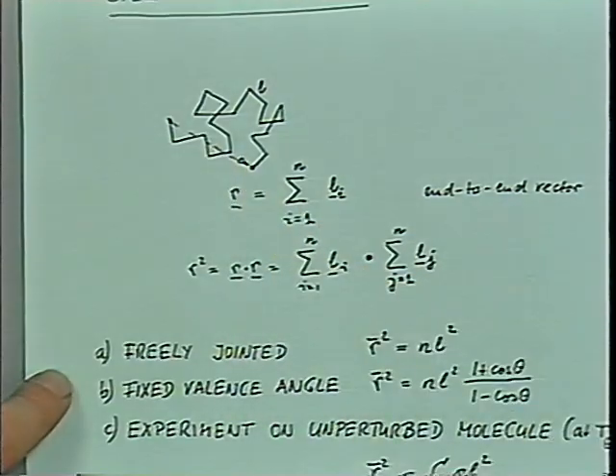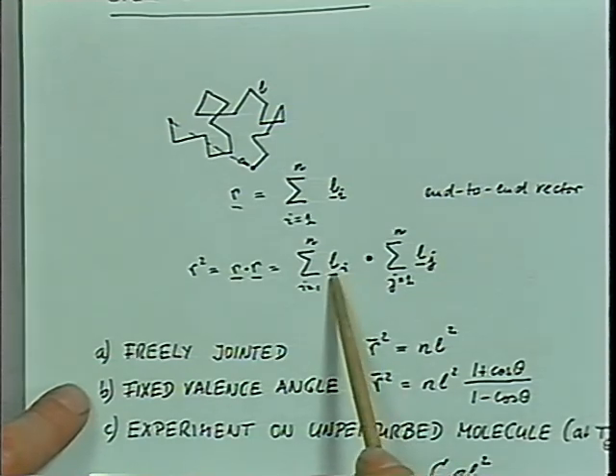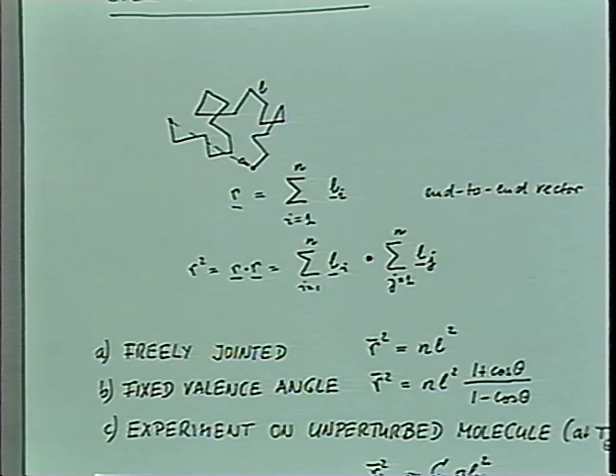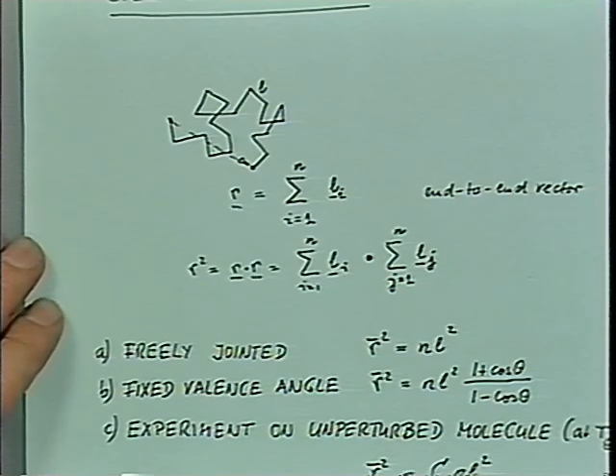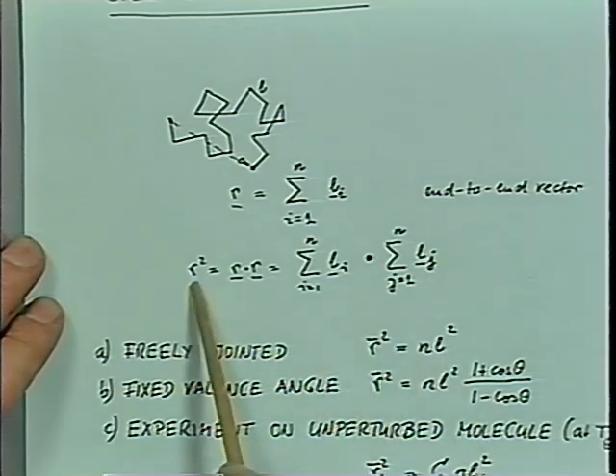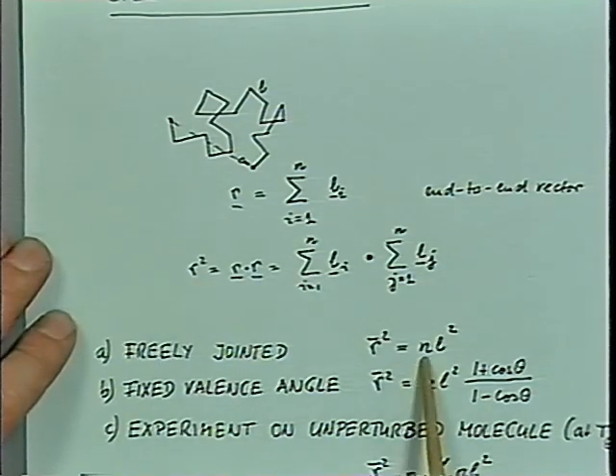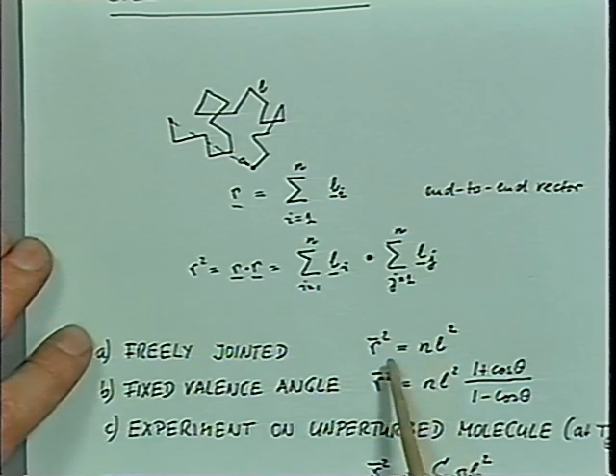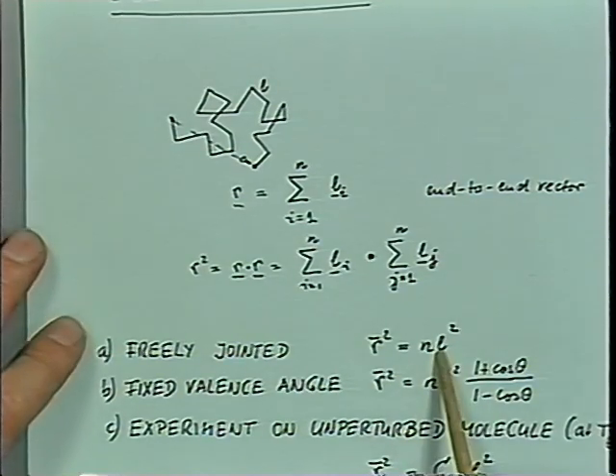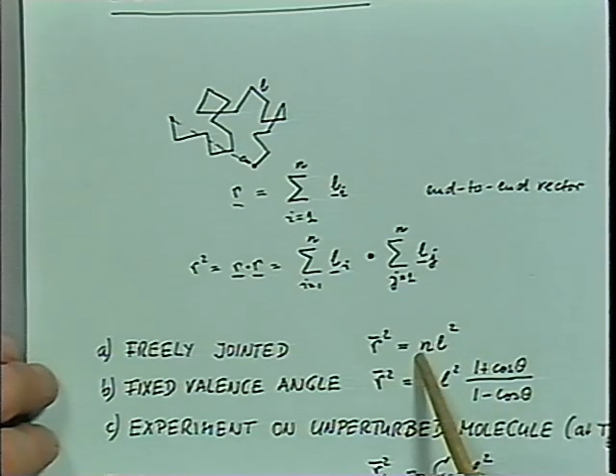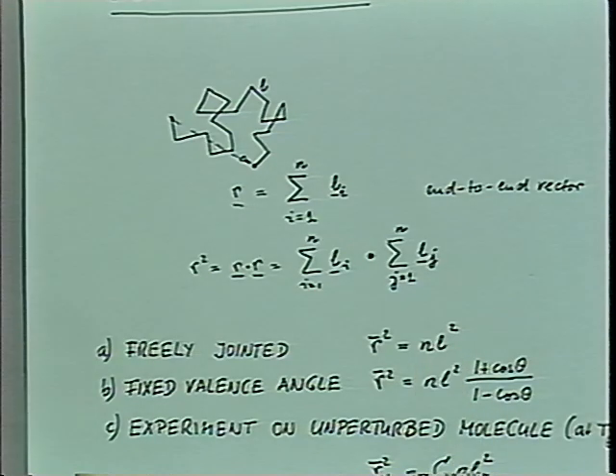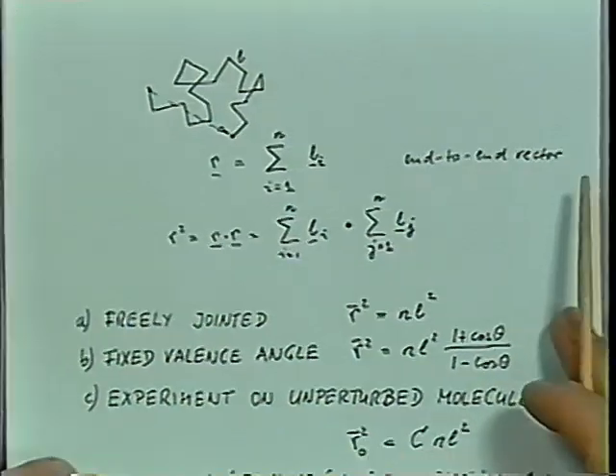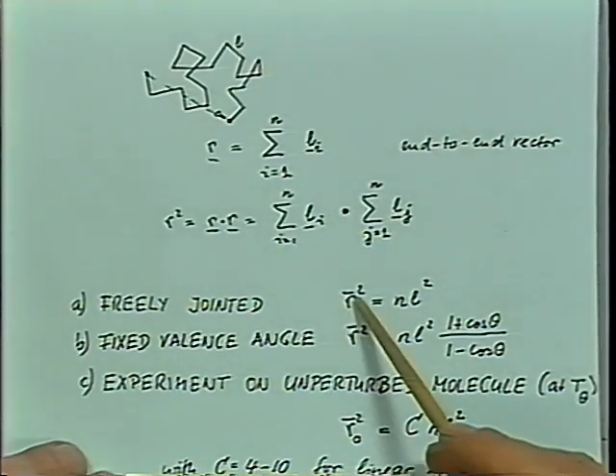And we can evaluate this expression for a statistically distributed system, a freely joined chain, with no restriction in this angle. In this case, the product of Li with Lj would most likely be 0, because they can adopt all probable directions. And then we end up having r squared being equal to the number of steps times the size of the step squared. So this end-to-end distance, or the square of that distance, is proportional to the molecular weight. The total length of the chain would be n times small l. So with increasing molecular weight, we are increasing the end-to-end distance squared.